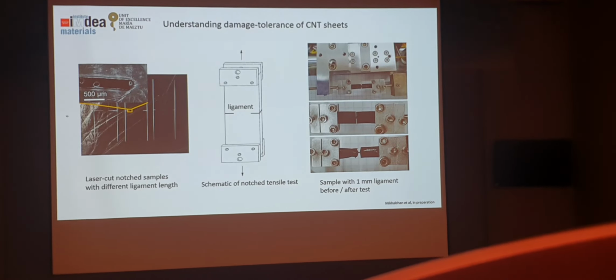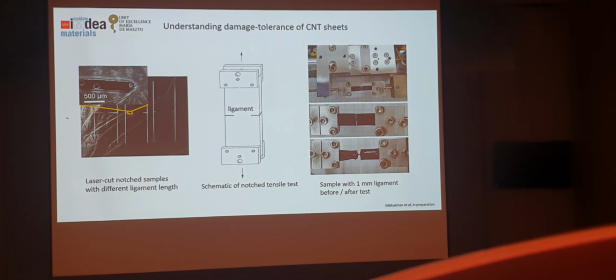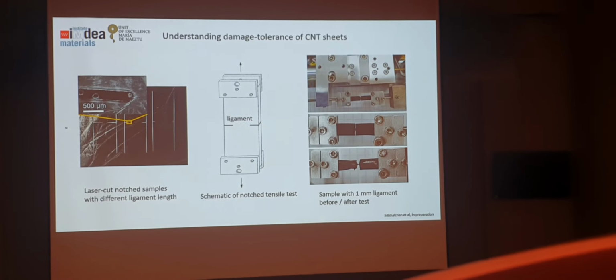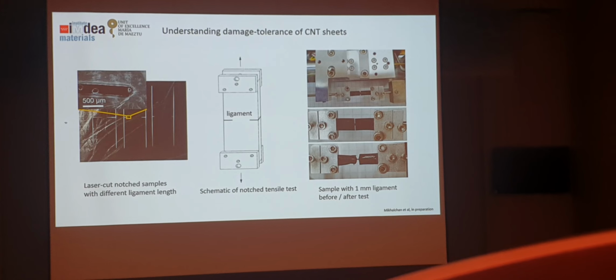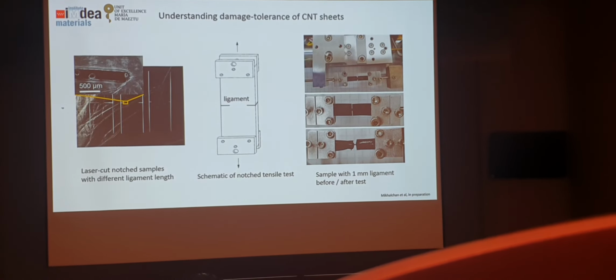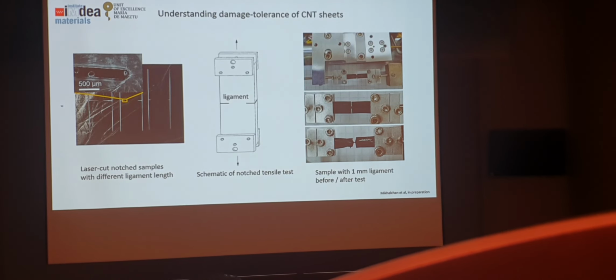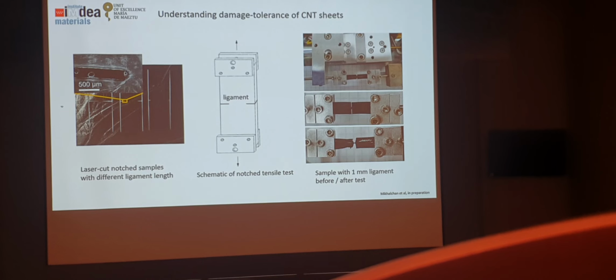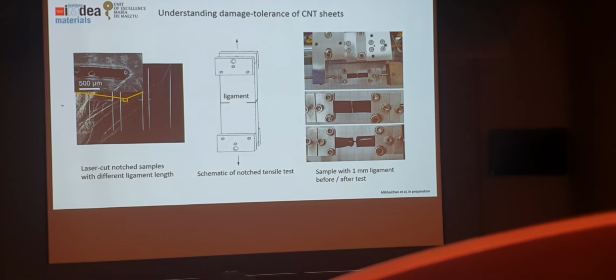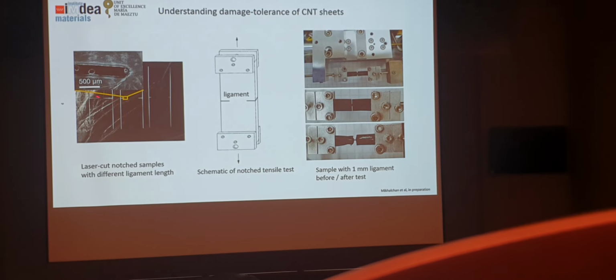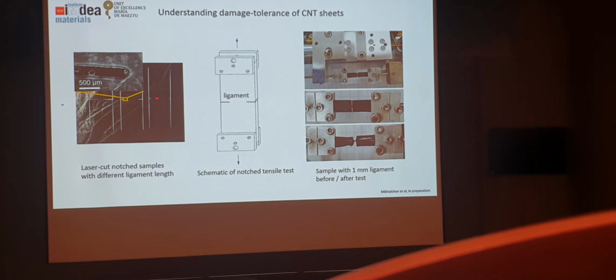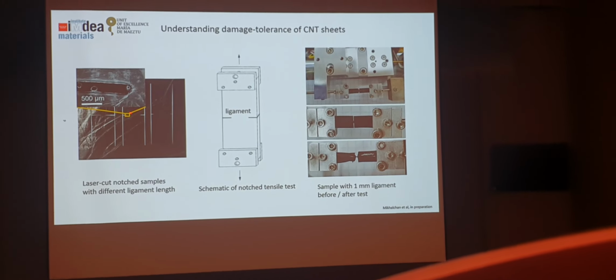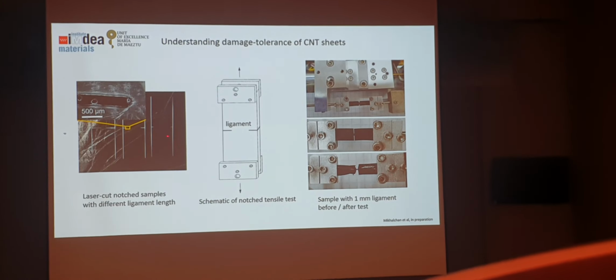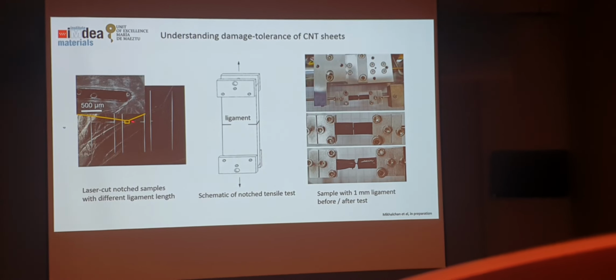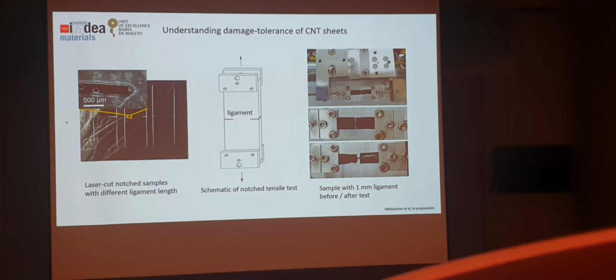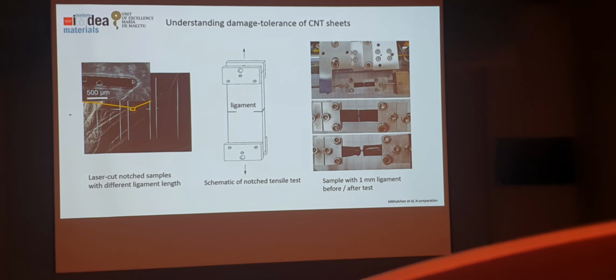And what we've been trying is to understand the mechanics of that system. So you can treat it as a polymer, and you have to, because in carbon fibers you would determine toughness through the fracture toughness, but that only applies to linear elastic materials. And we know that CNT sheets deform through a significant plastic deformation, so you cannot really determine the fracture toughness. Instead, what one normally does for these network materials is to make a notch of different sizes. So you produce a ligament and then do a tensile test and see how the fracture energy changes for different ligament sizes. So we cut these using a laser cutting machine with different ligament sizes. The ligament refers to the size that is unnotched, that we didn't cut, and this is what they look like under a tensile test.